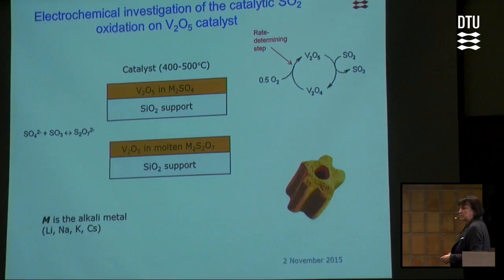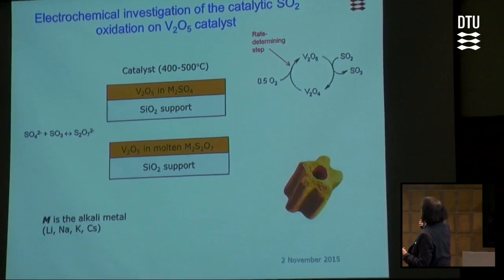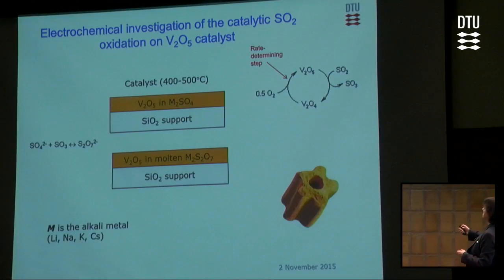Okay, so this first example, and people from Haldor Topsoe know this catalyst, it's one of yours. It's vanadium mixed with alkali metal sulfates on a silica support. When you have started this reaction and you produced some SO3, then it reacts with sulfates, producing pyrosulfates. At the temperatures at which this reaction works, as I told you, we have formation of a mixture of pyrosulfates, which are molten in these conditions. So we have a very good simulation here, a liquid electrolyte simulation. It's a solution of vanadium in a mixture of alkali metal pyrosulfates.